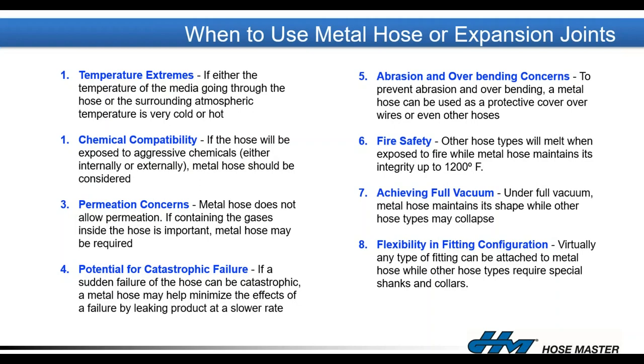Also, metal hoses are very versatile and they allow for great flexibility in fitting configurations. Pretty much any fitting that is made of a weldable material can be incorporated into a corrugated metal hose assembly and in any order. We routinely fabricate assemblies that might be what we refer to as a dog leg, where you have two separate hoses that are joined using a common pipe elbow between them. And those provide certain application benefits as opposed to a single hose that has to be installed in that 90 degree bend. By using that elbow fitting to perform that bend, it frees up additional corrugations in the length of that assembly to accommodate the movements and vibration of the application.